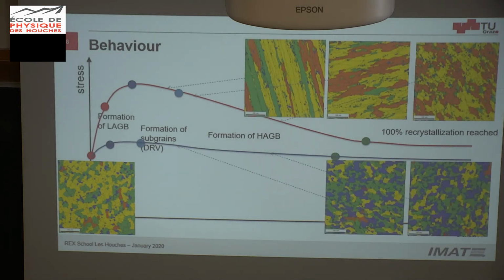Good, and this is how it looks if I go to 350 degrees or to higher temperatures. This is a GOS map, grain orientation spread map. Blue means low misorientation within the grains, and orange means high misorientation within the grains. So it goes for very, very large deformations until it really starts to dynamically recrystallize continuously.